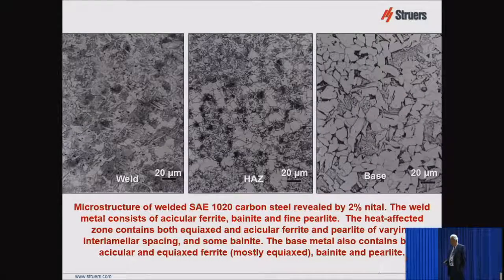And here's higher mag views at 500X using 2% nital, showing the weld metal, a lot of ferrite and bainite and some fine pearlite. And over here in the heat affected zone, we've got a lot more ferrite, the grains visible, and they're fairly equiaxed. Over here in the base metal, we've got ferrite, we've got the dark patches here are pearlite, these lighter patches are bainite.